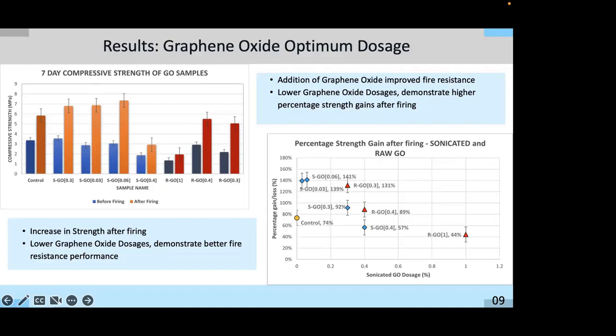So there's a lot of optimization here. But one of the challenges that we have is that once we have too much of, say, graphene oxide, there is a problem with dispersion of the material, and some overlapping of the material can actually lead to some decrease in strength. So we've seen that problem. As I mentioned before, we've looked at the process of sonicating versus no sonication, just to see whether some of these additional treatments do affect the performance. Okay.